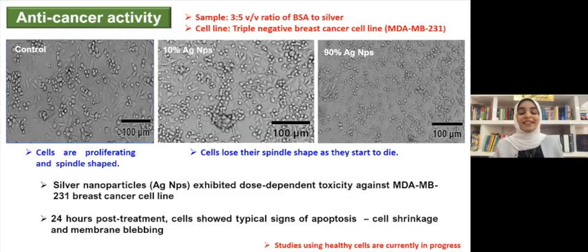So we looked at the anti-cancer properties of our silver nanoparticles. Here we used the sample of 3 to 5 volume to volume ratio of our BSA to silver nitrate, and we also used the triple negative breast cancer cell line. We obtained a control, and then we added 10% of our silver nanoparticles, and we added 90% of our silver nanoparticles. In the control image, you can see these are healthy breast cancer cells, so they're not affected by any silver nanoparticles. You can see that they're proliferating and have a spindle shape.